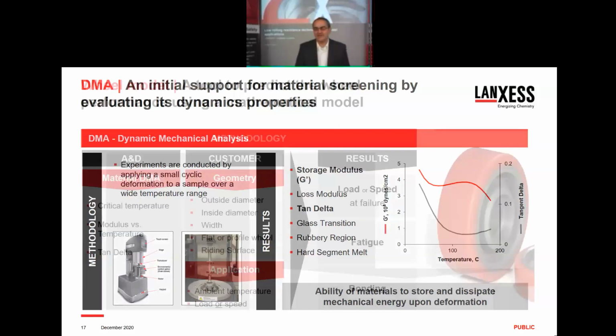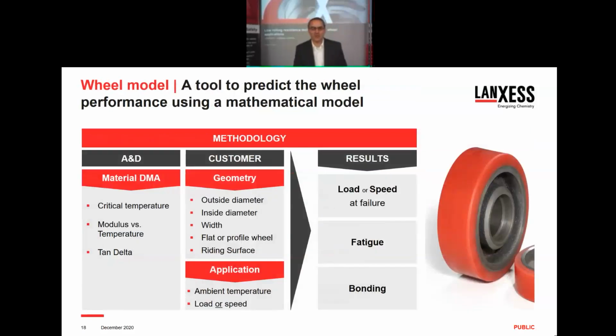Here's an example of kind of what we need and where we go with our wheel model. So from the LANXESS standpoint, we are the application development group, and the material side over on the left-hand side, what we do is we generate the data from DMA with the critical temperature, the modulus versus temperature, and we look at the tan delta. And tan delta is the relationship of energy stored versus energy lost. Our customers provide us usually with the geometry, the outside diameter, the inside diameter, the width, what's the profile of the wheel, and what's the profile that we're riding on.